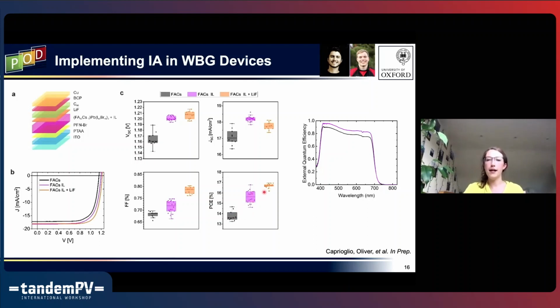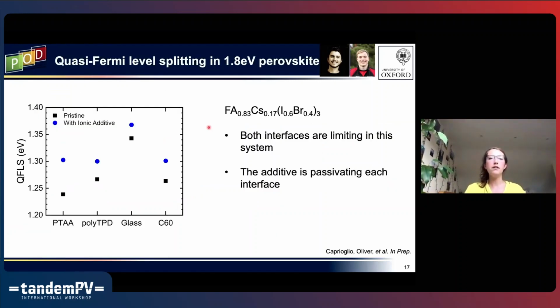So here we have our control device in gray, the ionic additive in pink, and then the recently popular lithium fluoride, which we'll talk a bit more about on the next slide, also improves device performance overall. One of the things I want to highlight is they get this really big boost in the VOC when they use this ionic additive. And from the EQE spectra, we can see that we just have better charge extraction over all wavelengths, better response.